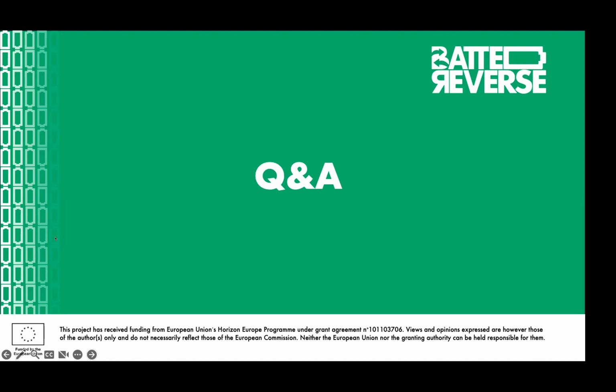Actually, I cannot totally answer this yet because we are studying this. Our chemistry department is now dipping the pouch shells into liquid nitrogen, and they are testing whether it affects the cells or not. We will be able to tell this within the next few months after the tests have been done. But with the one experiment that we have been doing right now, it didn't affect the cells, and they didn't actually cool. They cooled only to minus 30 because we gripped those off before they cooled to minus 160 degrees. So it wasn't a problem that time. But if we use deep freezing and have to freeze those for a longer time, I'm going to get the answer, unfortunately.